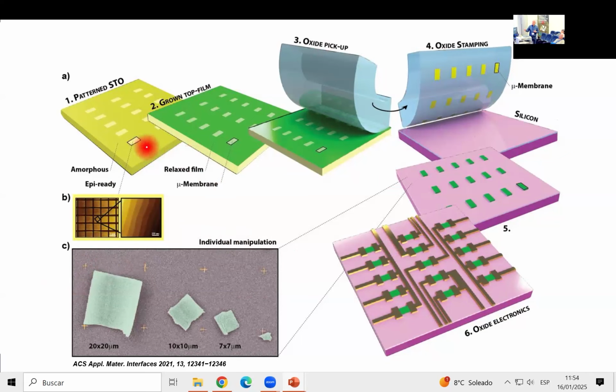It's a cartoon, basically. You can start with the patterning of the STO, as I'm showing here. You grow the material, then you stamp it, you sample it, and you move it. So you take the flakes from the substrate and put them onto silicon, for example. Then you do lithography, you connect this, and then you get oxide electronics. Interesting about it is that now you have a 2D material, which has many, many properties, and now you can make devices out of this. This is just an illustration of how you can use these membranes or another type of membranes for some applications.